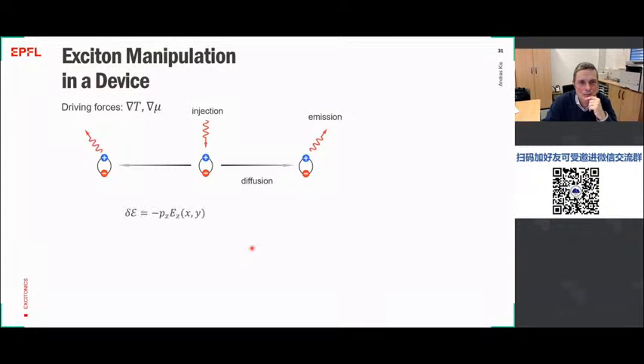And now, since the excitons have an electrical dipole moment, we can also change their energy by applying a vertical electric field. So this is the energy of the exciton or its modulation, the value of the dipole, and the application of an electric field in the z direction can change the energy of the exciton, which is diffusing in this heterostructure. And with this electric field, then we can establish control over the diffusion.